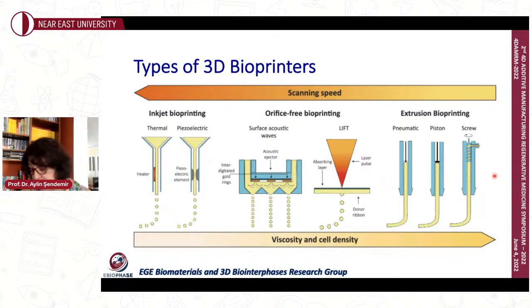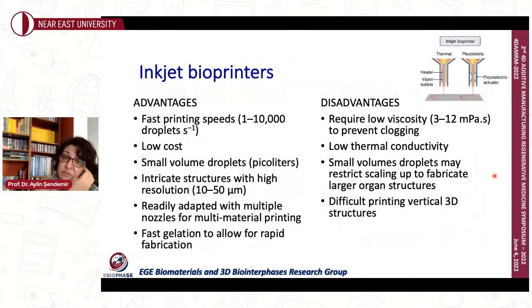Güllü Hocam, for example, in the examples that she had provided, they were producing the scaffold and then seeding the cells on those scaffolds, 3D printed scaffolds. In that case, because printing and cell seeding is performed separately, we don't need to worry about cell viability. But if we're trying to print the live bioink itself, the printing process becomes much more harsh, much more prone to lowering cell viability. That's what I will try to emphasize during this talk.